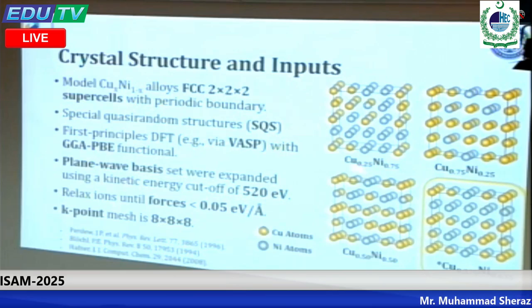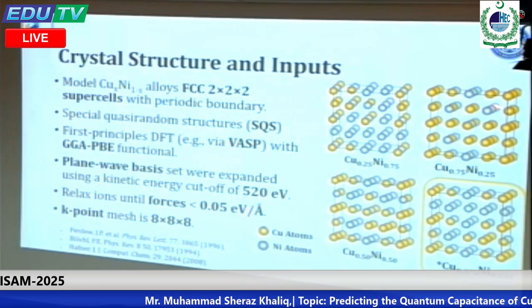Then we have to relax these atoms or ions until the forces on each atom due to their internal interactions are less than 0.05 electron volt per angstrom. And then the K-point mesh of the Brillouin zone is 8 by 8 by 8. So these are the basic inputs for the DFT in VASP to do the simulation.